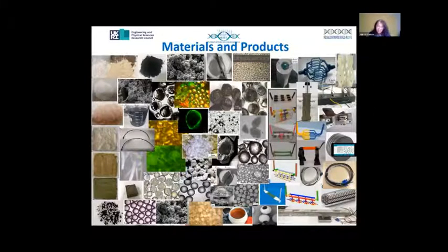And then we come to the large group of capsules, which is probably the area where we've done most of our work. So we have macro capsules with impregnated and coated lightweight aggregates, and also superabsorbent polymers or SAPs. On the micro capsules front, we have produced some from a number of different fabrication techniques with both mineral and organic cargo and shell materials, and for both physical and chemical trigger. We focus on sodium metasilicate and other silica-based cargo for physical damage, and oils, natural and mineral-based compounds as corrosion inhibitors for chemical damage.